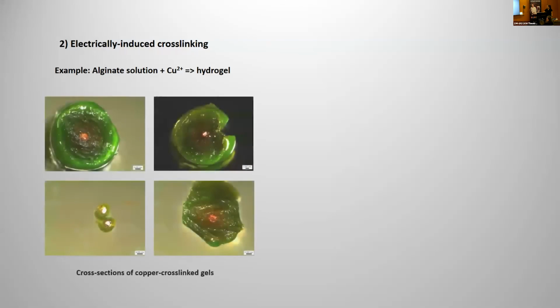Now, another thing that we came across as being useful was, when you make your polysaccharide hydrogels, usually you go and dump them in a cross-linking bath of salt. We found that all you want to do is spit out divalent cations into these gels. So why not directly do that through oxidizing metal? I know it looks a bit strange, but these are cross sections of gels that we made by growing them directly onto copper fibers.